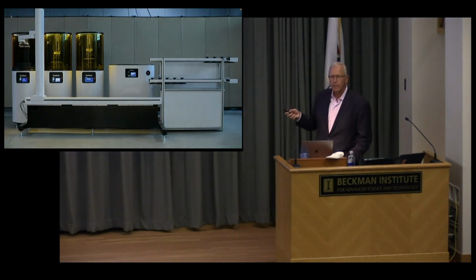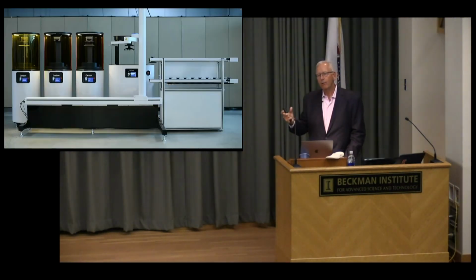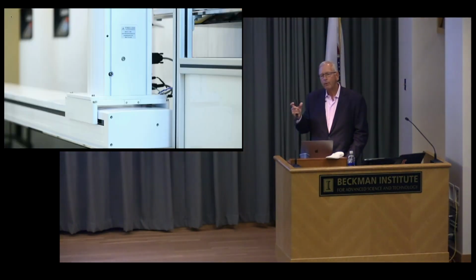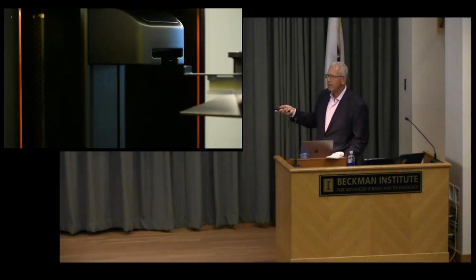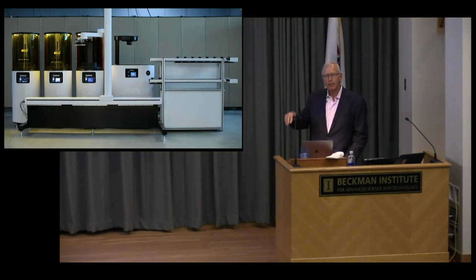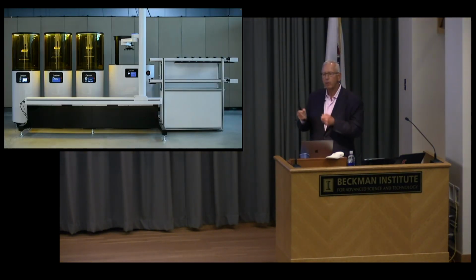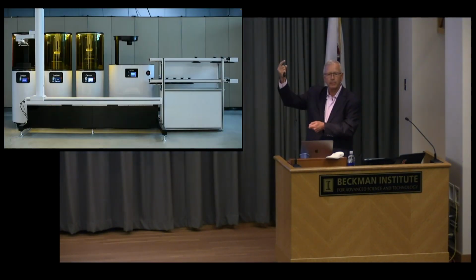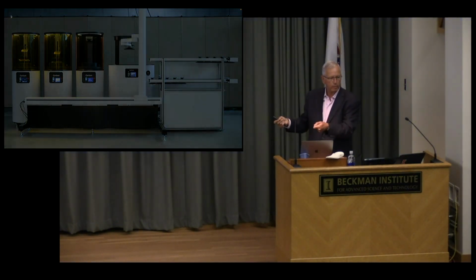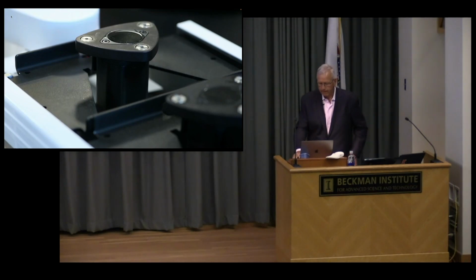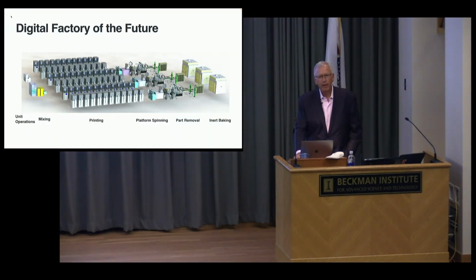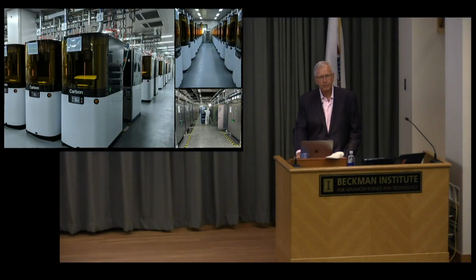Every window is actually not identical. We build them within a nominal spec. Every window's got a near-field communication tag. We build the windows within a nominal spec, then we do a bunch of measurements, and you put that window into that printer, it pings the cloud and brings down specs just for that window, so that it prints perfectly. You can start envisioning bigger factories, and then you can start to build them with bigger printers.